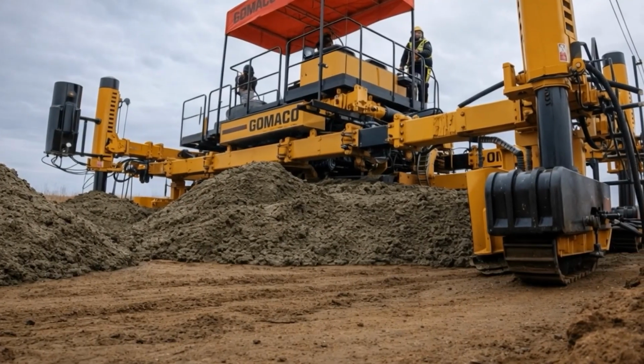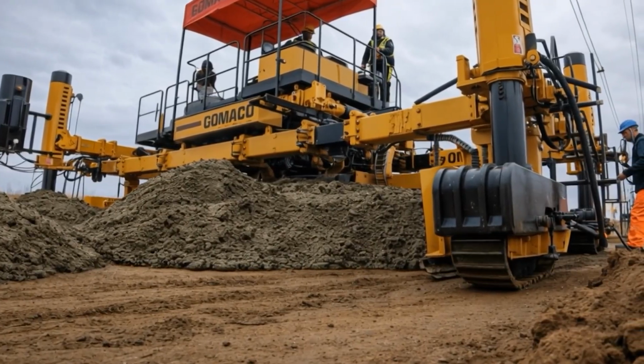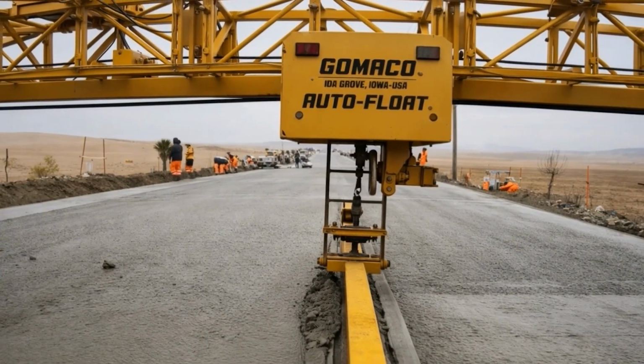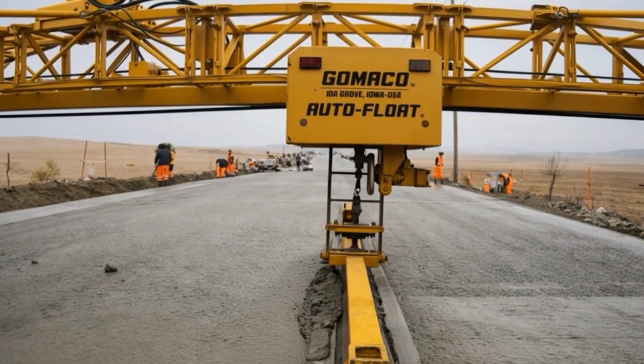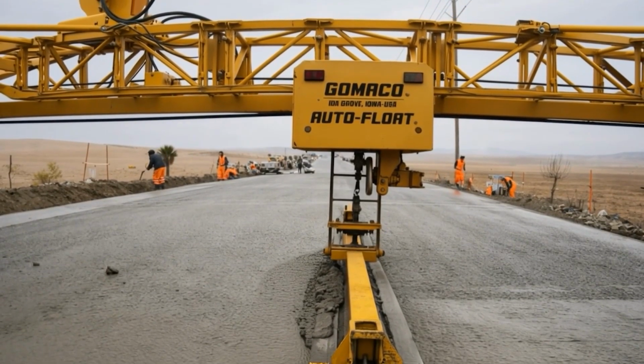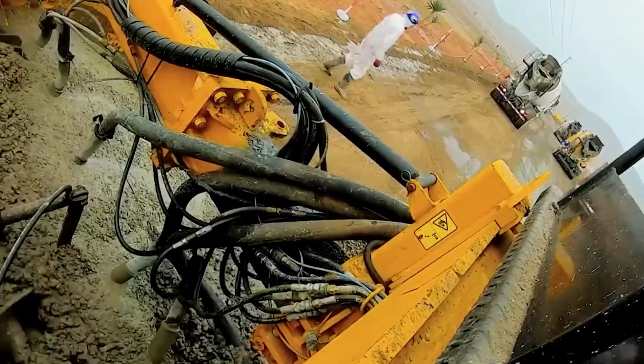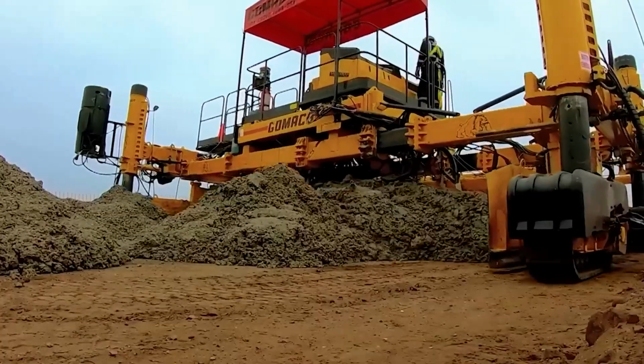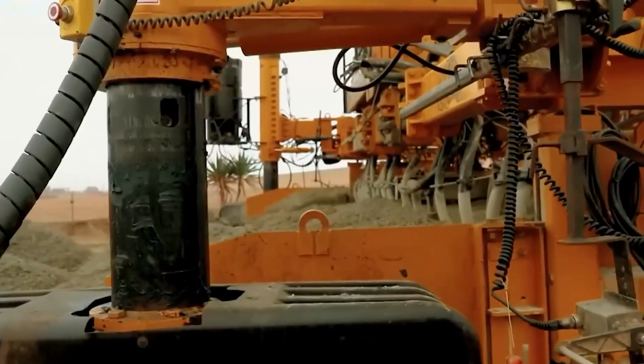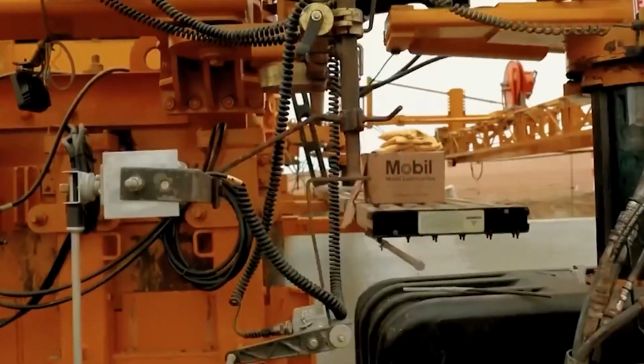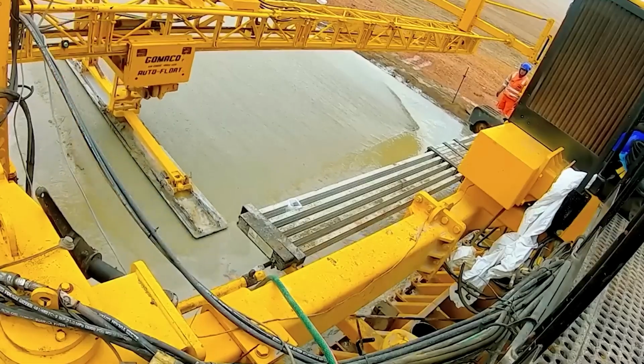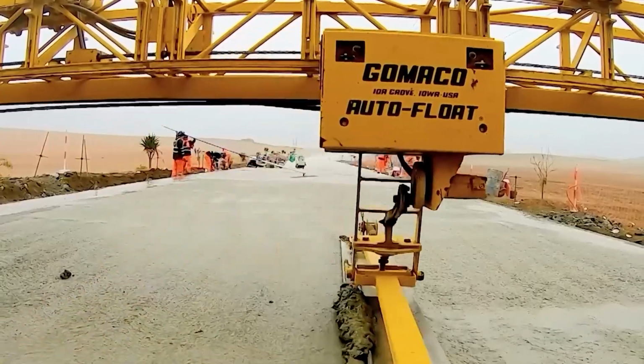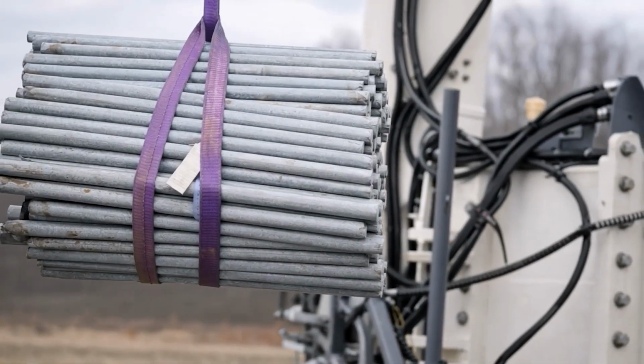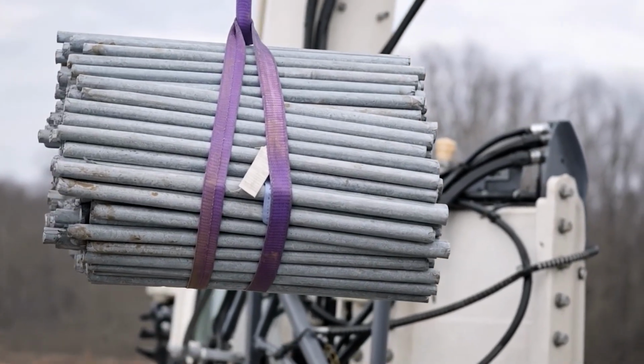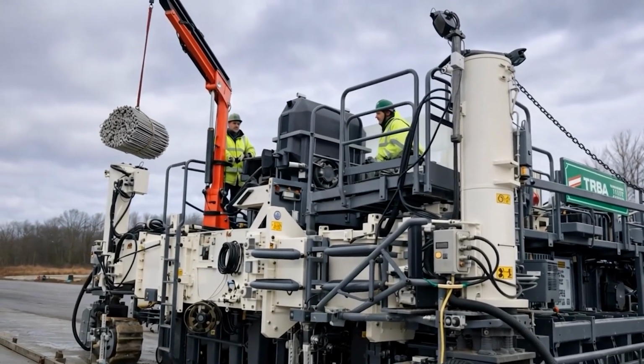The paver is equipped with vibratory plates and forming side molds, which simultaneously compact and give the concrete its final shape while it is still plastic. Inside the machine, an auger or distributing mechanism continuously moves the mix forward, evenly spreading it in front of the entry into the forming zone. Laser sensors, GPS systems, and three-dimensional navigation technologies control every centimeter of the surface. Thanks to this, the road turns out perfectly even and exactly matches the design parameters.